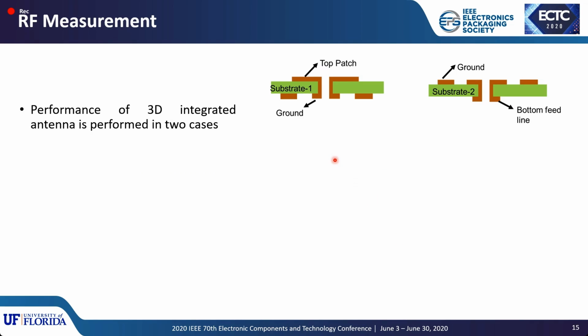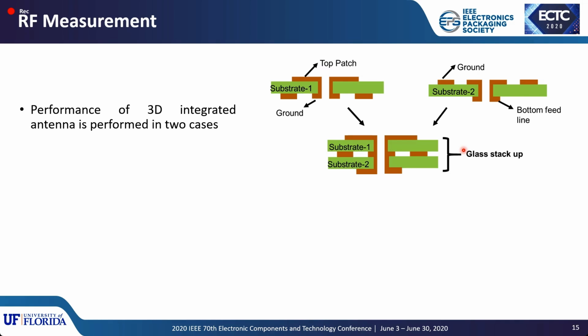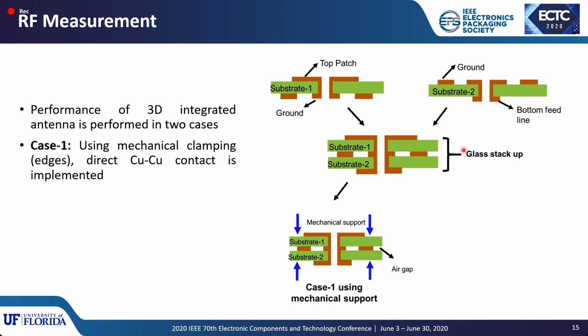RF measurement of this 3D integrated antenna is performed in two cases. As you can see, we have two substrates with the ground and the patterns for the top patch and the bottom feed lines. These two are integrated together to form a glass stack. In the first case, we use mechanical support in order to get copper to copper contact between both the substrates. And you can also notice that there is a clear air gap between both the substrates.